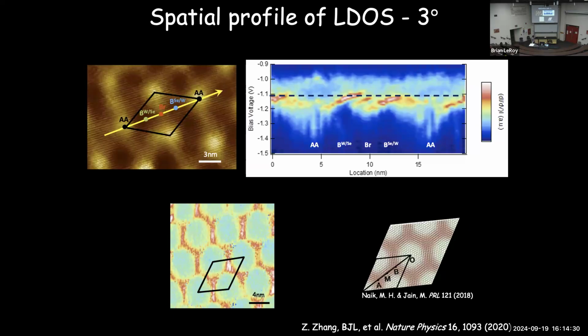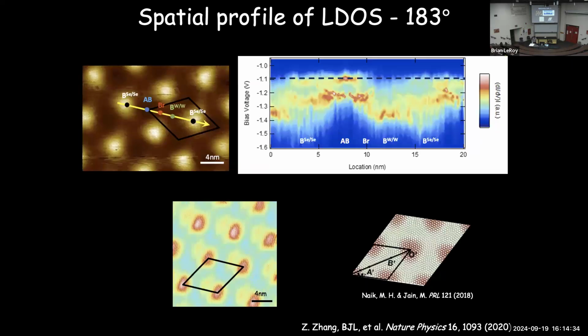But if you look back here, this is on the edges of these hexagons up here. If we compare that to here, these are now in the center of the hexagons. The hexagons have low density of states. There's actually a slightly brighter on one site than the other on the inside of the hexagon. And that also agrees fairly well with the theory calculations.